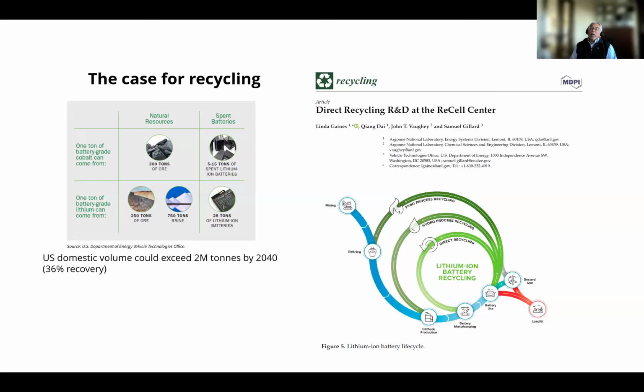So that's a use that I think we have to seriously consider. And it poses an energy engineering challenge to figure out how we are going to efficiently and cost effectively cycle those batteries from electric vehicle use to another use before they go through these other recycling strategies, which essentially involve taking the batteries apart and restoring them or recovering the materials. So you can see there's three major recycling strategies once you've decided that the battery no longer can be reused on its own. And those include pyrometallurgical processes, which is essentially smelting and combustion. The combustion actually can be a good thing because if you have been following some of the hazards of recycling any kind of lithium battery, the flammability of the electrolyte is often the most dangerous part of handling and storage or shipment of these batteries, whether they're new or being recycled.